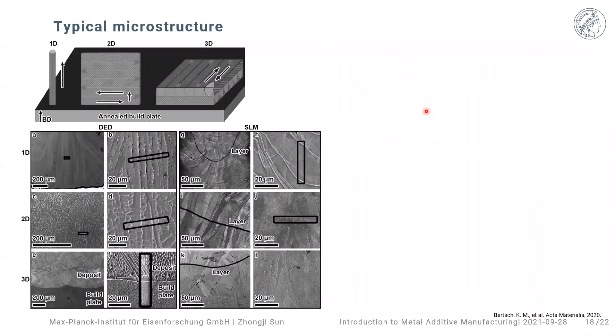Once they moved down to the middle of the bulk sample, they started to see typical cellular structures. Their conclusion is that the cellular structures are nothing but an evolution of the growth mechanism of these nanocrystalline grains, which is also very interesting. Another group from the US did a very interesting experiment: instead of only building a 3D sample, they also built 1D and 2D structures. A 1D sample is simply just one dot of laser powder deposition — they did this because in 1D there is no surrounding material, so the part does not experience residual stresses from adjacent material shrinkage.